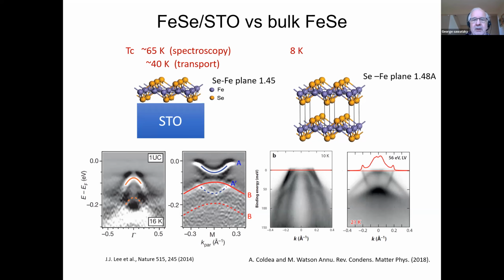We actually don't know really, as far as I'm concerned, what the chemical composition is. We also don't really know what the structure is. But we know something about the electronic properties. And if you put iron selenide on STO and dope it with electrons, you get a transition temperature up to 65 Kelvin, at least from spectroscopy, and that's from tunneling or from photo emission, actually looking at the superconducting gap and so on. From transport, it's more like 40 Kelvin that you get.